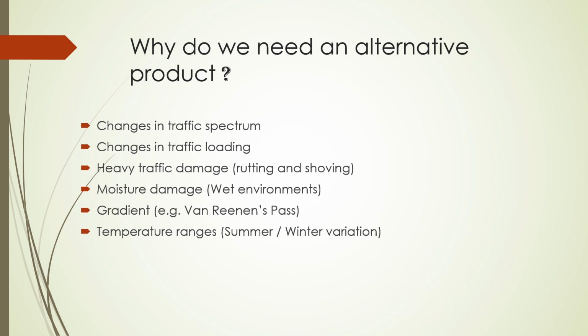Moisture damage: it has a good result in a wet environment. And the next one is gradient. And next, temperature range. It has better results in summer as well as in winter. When the road surface temperature begins to approach the softening point of bitumen, the high surface temperature causes the asphalt to become plastic and then deform very easily, resulting in rutting. Whereas the heat retention property of steel slag is an advantage. That's why we use an alternative product.